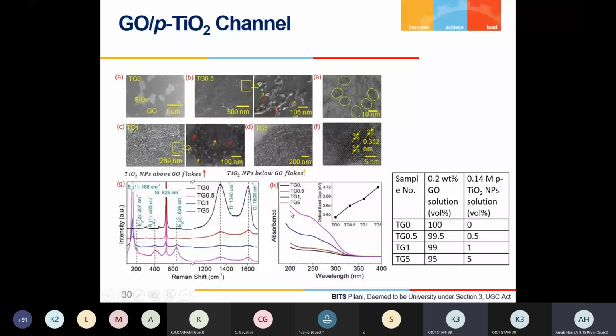Raman spectroscopy shows the D and G peaks, as I explained in the previous slides. But additionally, it shows the peaks related to titanium dioxide at the lower wavenumber. And this is the UV-visible spectroscopy to estimate the band gap. The band gap is increasing in the composite material. You can see here the optical band gap is increasing from 3.6 to a slightly higher value.